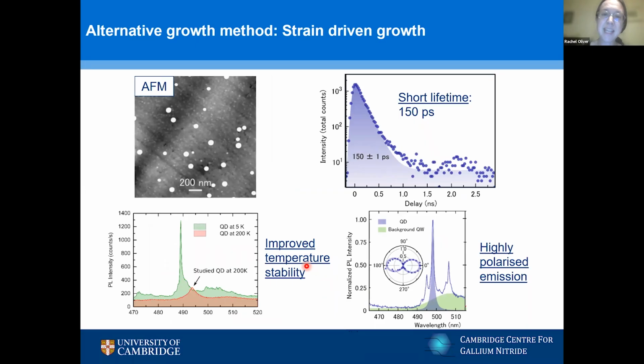It's just worth mentioning that we don't necessarily do all our quantum dot growth on the A-plane using this droplet epitaxy approach. We do also grow dots in a slightly more traditional strain-driven method. It's a bit like SK growth, but not quite. There are some distinctive weird issues with it that make it dissimilar. But these quantum dots nonetheless are grown in a more traditional method, and they show very similar properties to the droplet epitaxy dots. Very short lifetimes, down to 150 picoseconds in this case, good temperature stability. Here we're showing a quantum dot which is losing intensity at 200 Kelvin, but still clearly detectable in emission. And this highly polarized emission that we saw again in the modified droplet epitaxy.